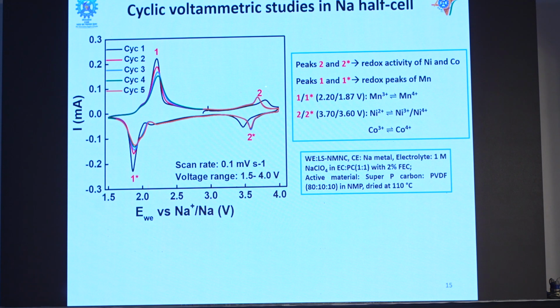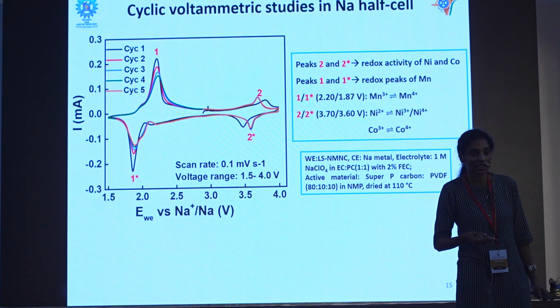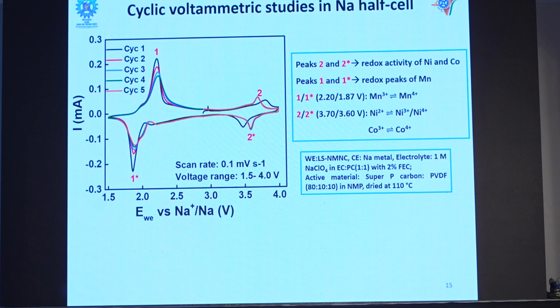We have an electrochemical reaction going around 3.5 volt. We mark it with 2 and 2 star, and we believe it is the activity of nickel and cobalt. And then we discharge the material to a voltage lower than the initial voltage. When we go below 2 volt, we are getting a new electrochemical activity around 2 volt. And this new electrochemical activity could be associated with reduction of manganese 4 plus to manganese 3 plus.